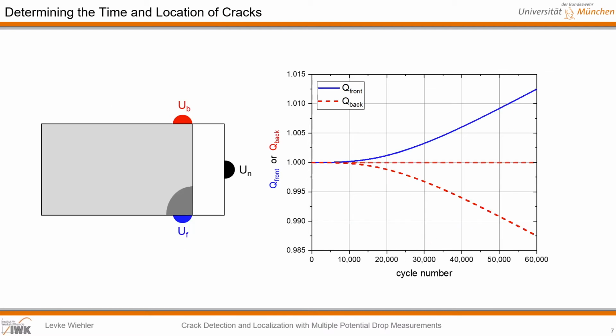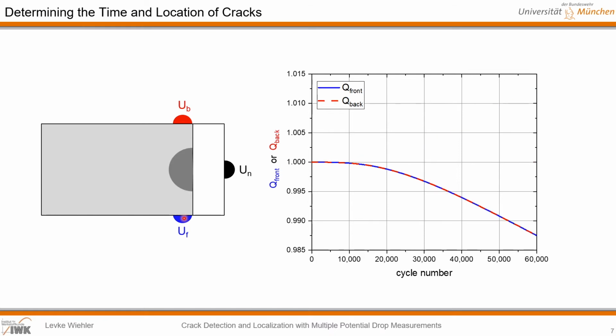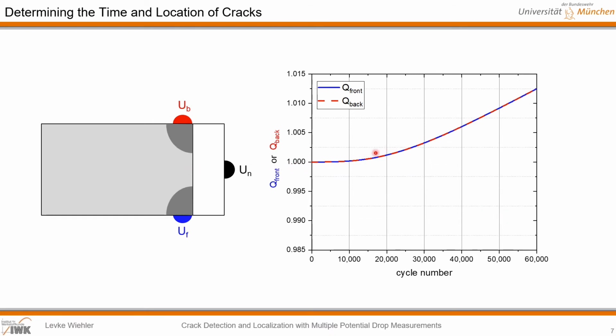Let us take a look at the first case. If Q front increases while Q back decreases or remains constant, a crack is initiated near the front side of the specimen. Remember, each case also applies to the opposite quotient. Case B, if both quotients drop, a crack is initiated in the center of the notch. Because the potential on the narrow side of the specimen increases and forms the denominator of the two quotients, both quotients decrease. And the last case, if both quotients rise, cracks are initiated on both sides of the specimen.